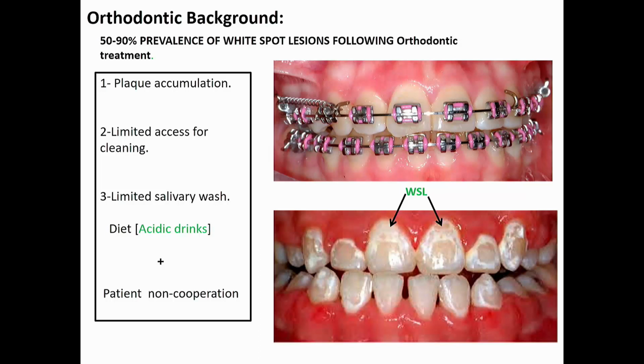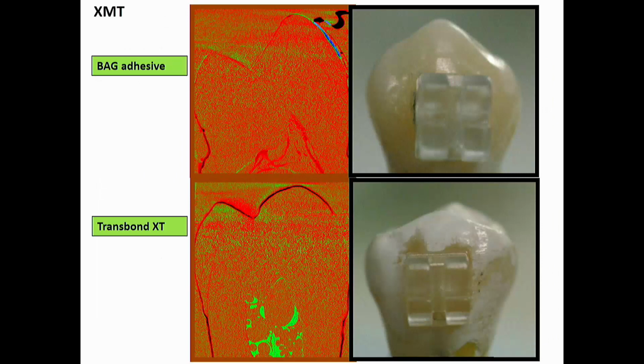So what we've been doing is putting bioactive glass into these adhesives, and the top one here shows a tooth with a bracket bonded with a bioactive glass adhesive and then immersed into artificial saliva at pH 4 for 18 hours. And you can see there's no whitening of the tooth surface. And this is the difference image in the X-ray microtomography, and there's no evidence of any demineralization of the enamel surface.